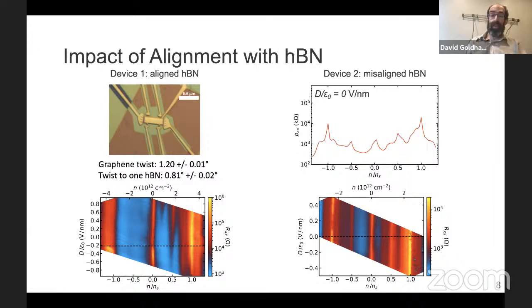It turns out that graphene is resistant to localization because of its topological structure, or let's say because of the structure of its honeycomb lattice, and if you don't do something to break the symmetry of the system, the resistivity of a single sheet of graphene cannot be larger than of order the quantum of resistance, or more specifically about 20 kiloohms in this case. And so a couple of kiloohms is a very typical resistance for a graphene sheet or two.